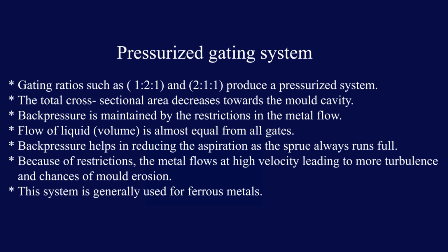In a pressurized gating system, gating ratios such as 1:2:1 and 2:1:1 produce a pressurized system. The total cross-sectional area decreases towards the mold cavity. Back pressure is maintained by the restrictions in the metal flow. The flow of liquid is almost equal from all gates. Back pressure helps in reducing the aspiration as the sprue always runs full. Because of the restrictions, the metal flows at high velocity, leading to more turbulence and chances of mold erosion. This system is generally used for ferrous metals.